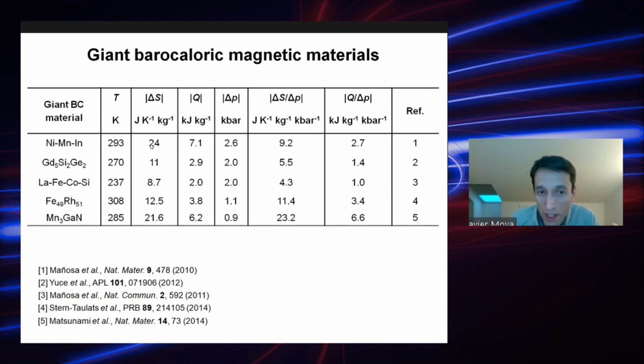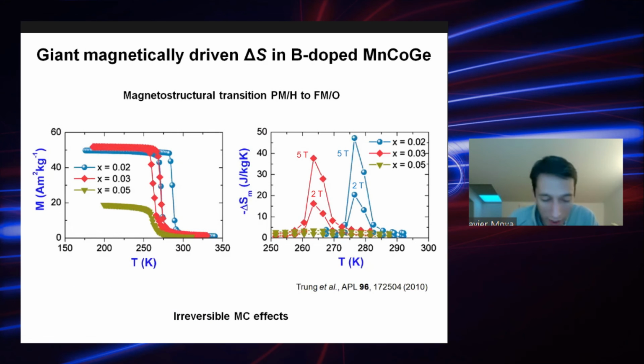Normally an entropy change of around 20 joules per Kelvin kilo is what we call a giant effect in this solid state caloric community. So something that we wanted to investigate is what happens when the materials have very large hysteresis. Because something that is important is that the effect is reversible, because you need to be able to drive it when applying field and then undrive it when you remove the field. And there are some magnetic compounds that are actually not that reversible when they apply a magnetic field.